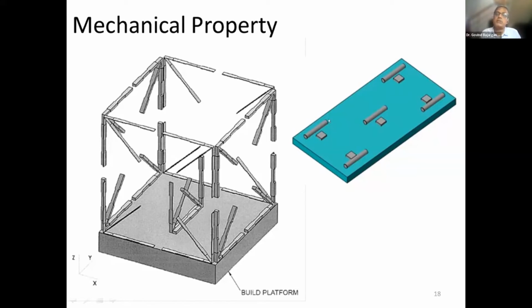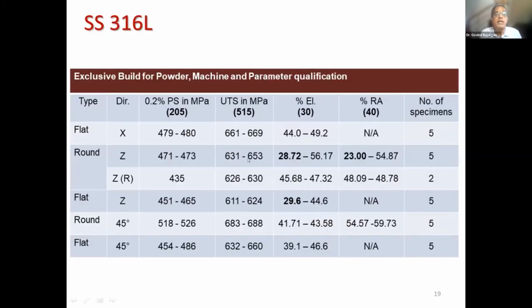ASTM talks about building 5 coupons at 5 different locations on the build platform along with the density coupons. So what we decided is we optimized that approach and went for some 25 to 30 coupons along with density coupons. And this one result I am sharing for 316L: when around 25 coupons were printed, we saw that 2 coupons in Z direction are showing lower elongation. Otherwise, properties are more or less consistent. When it was analyzed, it was found that it has something to do with one parameter called dosing factor, wherein material powder is added in front of the recoater blade, and the quantity got affected for some reason.